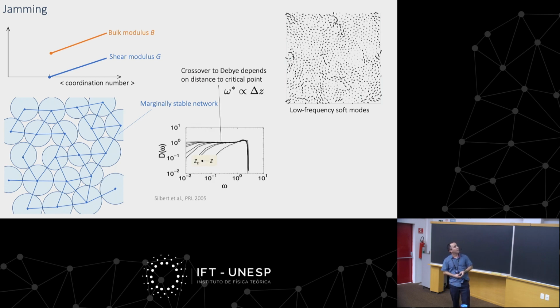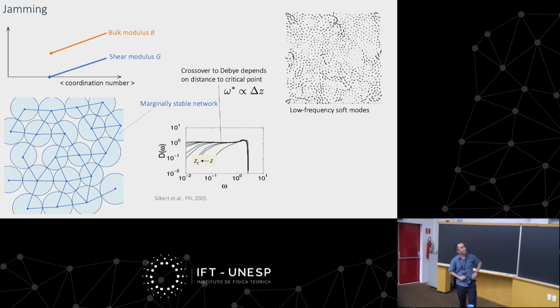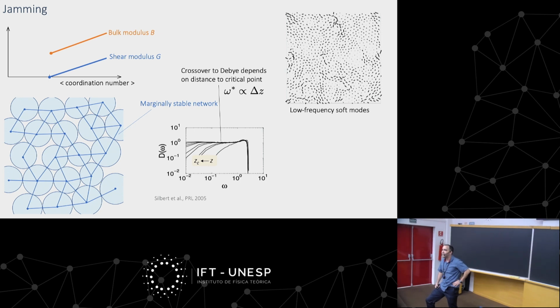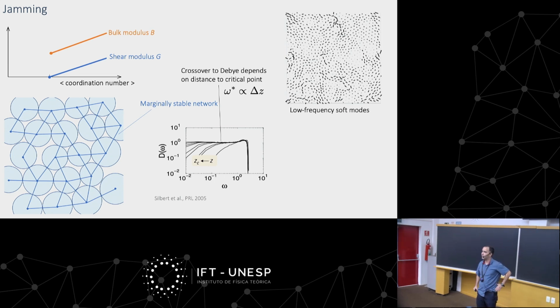So you can look into this and describe this jamming transition. As you get close to this jamming transition, if you look at the density of states, for instance, at lower frequency, you have this enhancement of the population of these low frequency modes. So this is, yes, go ahead, Nita. So you can, for instance, write down some elastic definition of bulk and shear modulus. Yeah, yes. So you describe, for instance,